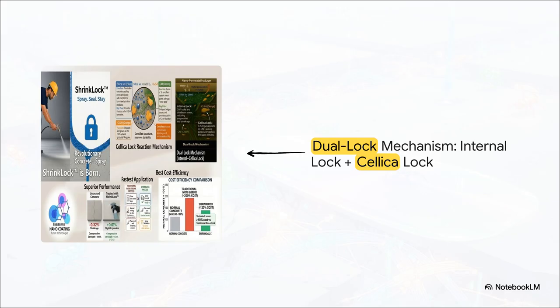The internal lock acts like a microscopic sponge, trapping critical moisture inside the pores so it doesn't evaporate too fast. At the exact same time, the Cellica Lock triggers a secondary reaction. It forms a CSH gel, that's calcium silicate hydrate, which physically fills up the microscopic capillaries. It locks the moisture in and builds a nano network to strengthen the whole structure.